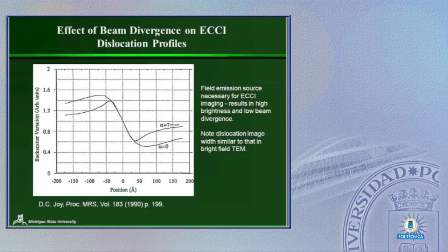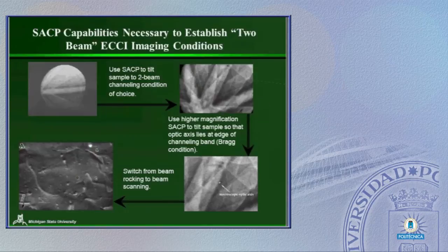The other thing worth noting on here, if you look at these peak to background positions, the widths of the dislocation lines are similar to that you'd see in bright field TEM imaging. That's about as good as we're going to do. We can't set up anything like a weak beam condition like you get in a typical TEM, because here we're really limited by the probe size in terms of our resolution, rather than some of the other things associated with weak beam microscopy.